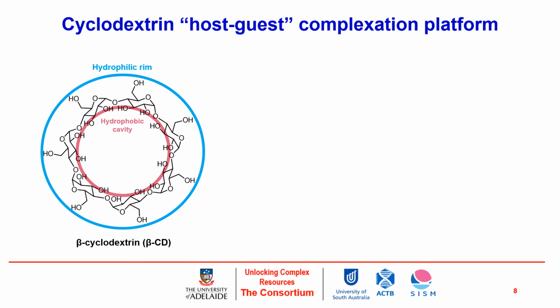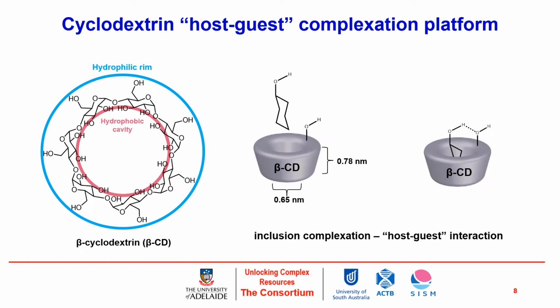Now, one of the key features of all of these flotation frothing agents is that they are hydrophobic molecules. Cyclodextrins come in a variety of sizes that is dependent on how many sugar structures are bound into their ring. So we worked with beta cyclodextrin on the basis that its size complementarity was sufficient that it should bind well with the compounds of interest that we have. The reason that these have a hydrophobic cavity is that a lot of the hydrogens that are projected off of a certain orientation of these sugars that are arranged in a ring are able to facilitate van der Waals interactions and hydrophobic binding capabilities within that cleft, whereas the rim or the secondary hydroxyls that are projected out from the cyclodextrin structure, shown on the left-hand side of this slide as a blue ring, are the hydrophilic surface.